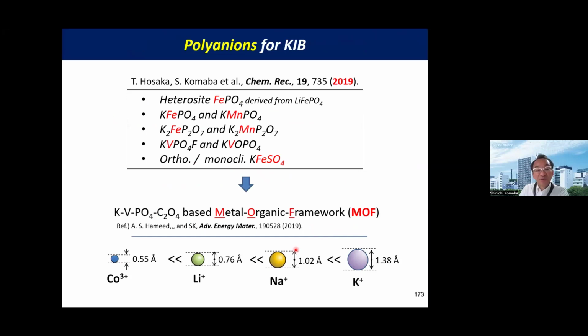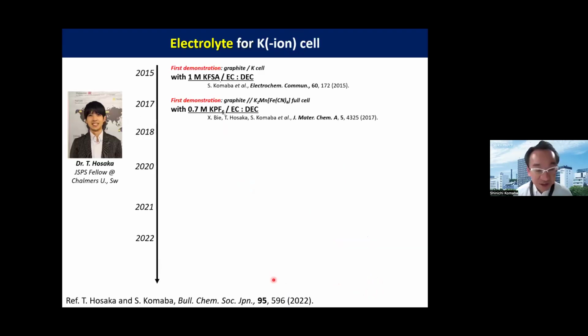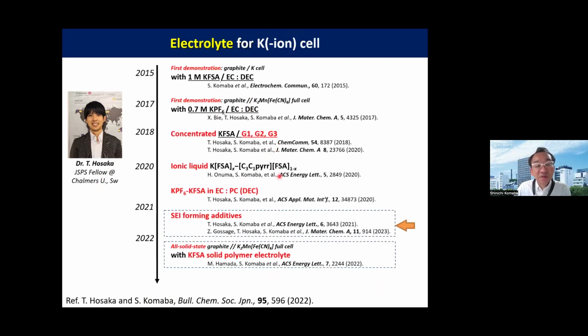And not only Prussian blue open structures, we have some good positive electrodes based on polyanions, potassium-containing iron or manganese compounds. And not only polyanions, metal organic frameworks should be advantageous for potassium insertion because its ionic size is larger than sodium. Electrolyte solution is another issue. During Hosaka's PhD period, he mainly contributed to finding new electrolyte solutions, not only carbonate ester, but also glyme, ionic liquid, SEI formation additive, and polymer electrolyte to achieve all solid state sodium and potassium ion batteries.